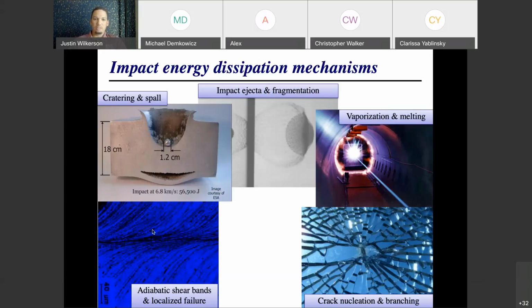So this figure here in the top left is a really nice visualization of spall failure. So you had an aluminum projectile that comes from the top down, and it impacts this armor plate of aluminum as well. And when it does that, it impacts at 6.8 kilometers per second, so an incredibly high velocity. And the projectile burrows in and creates a crater, right? So it kind of looks like if you were to take a rock and throw it in a pond, you would get kind of a splash, and then it looks like that's frozen. But in fact, this is all just plastic deformation.